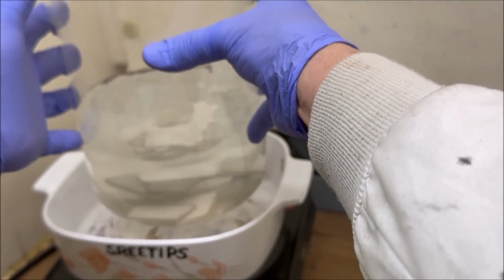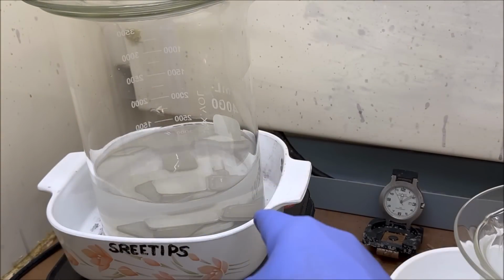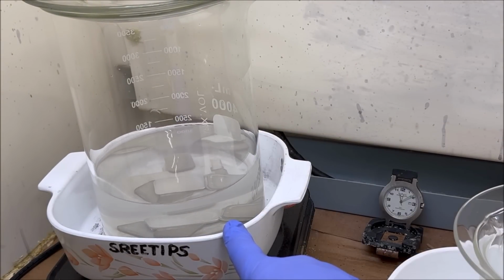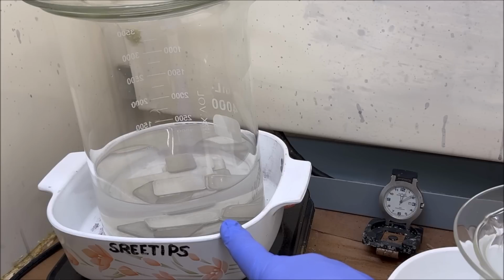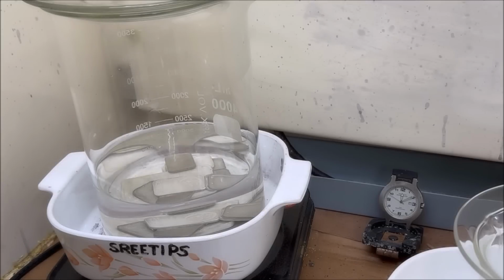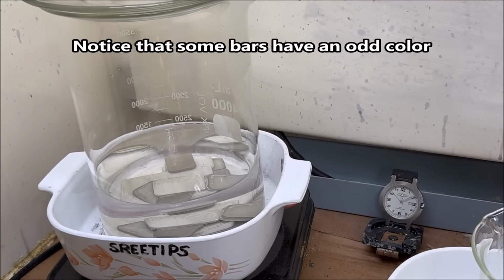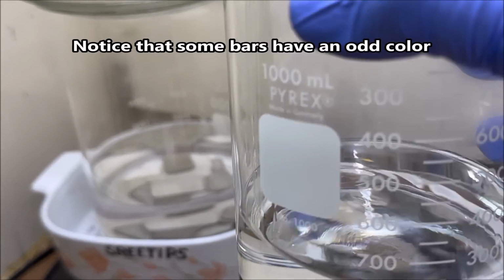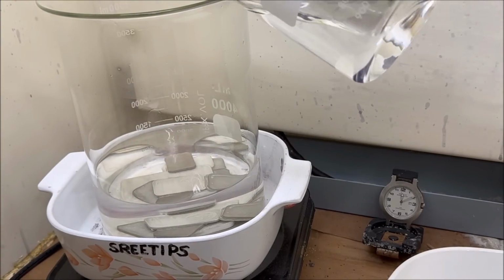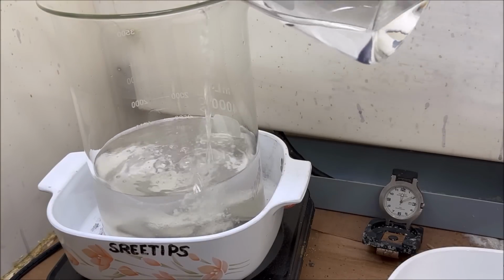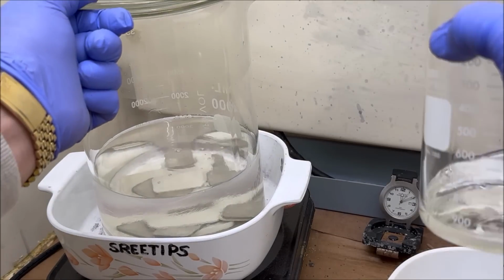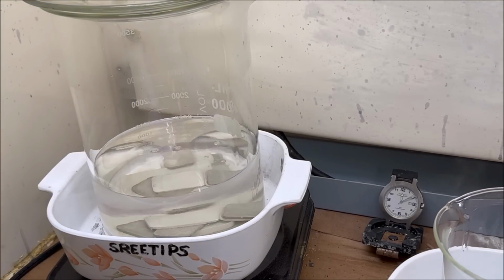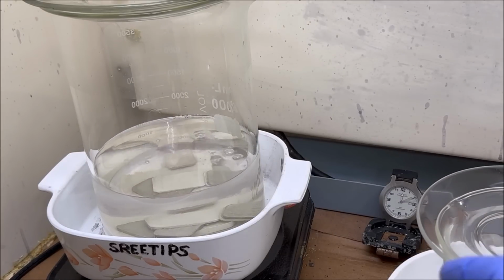Normally when we dissolve sterling silver, we'll expect to see a blue colored solution here because sterling silver has copper alloyed with it. This should be 999 fine silver, so it should be colorless when we get done, like water. That reaction does not look very vigorous, so I'm going to pour in a little bit more of my nitric acid. I can always add more, and I can't take any back out if I overdo it and we start foaming over to overflow the beaker. So it's best to add small amounts slowly.